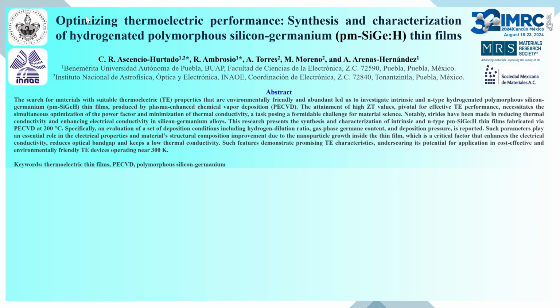The attainment of high ZT values, pivotal for effective thermoelectric performance, necessitates the simultaneous optimization of the power factor and minimization of thermal conductivity, a task posing a formidable challenge for material science. This research presents the synthesis and characterization of intrinsic and n-type hydrogenated polymorphous silicon-germanium thin films fabricated via PECVD at 200 degrees Celsius. Specifically, an evaluation of a set of deposition conditions including hydrogen dilution ratio, gas phase germane content, and deposition pressure is reported.